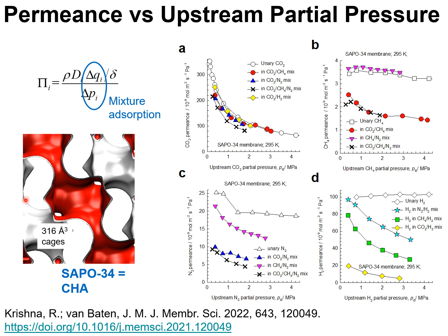The message to emerge from this graph is that mixture permeation in cage window structures is more easily predictable than for materials that contain topologies with pore dimensions larger than 5 angstrom, because in these structures such as chabazite, DDR, slowing down effects and traffic junction effects are not relevant.